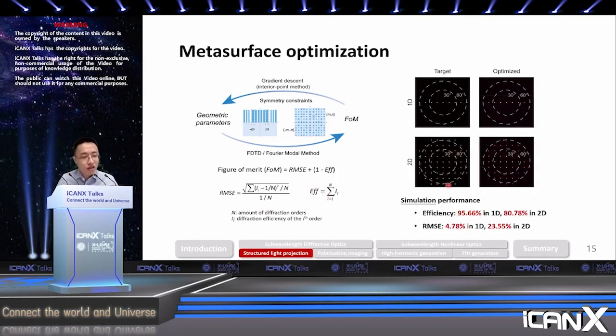Through our simulation and optimization, which takes maybe a couple of hours for the 1D structure and maybe a couple of days for the 2D structure, we can get total diffraction efficiency greater than 95% in 1D and greater than 80% in 2D, with an RMSE value of less than 5% in 1D and a little above 20% in 2D. To give you a perspective, this is comparable or even better than the state of the art for conventional DOEs, with the big difference that we are doubling the field of view, increasing it from 60 to 120 degrees.